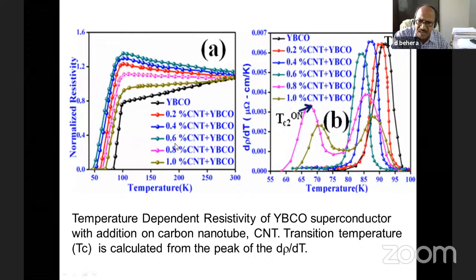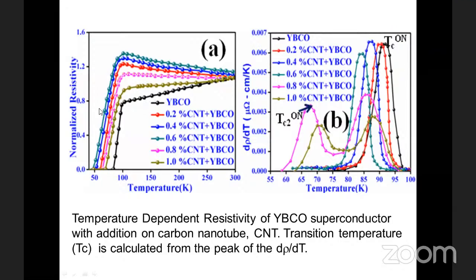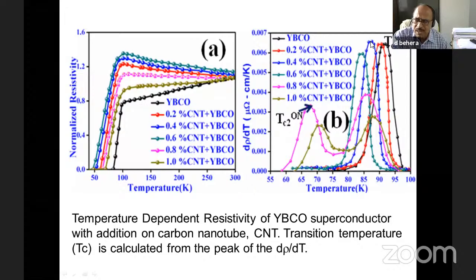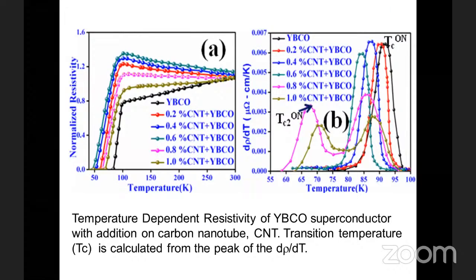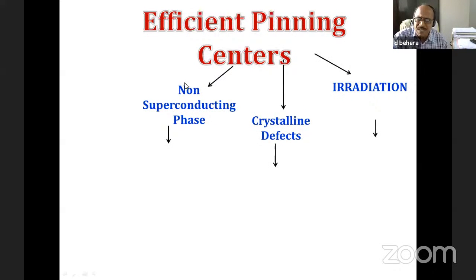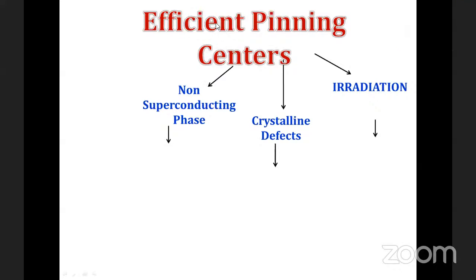My students prepare this material and measure the critical current density. The TC of the material can be measured from the derivative of the curve. It gives you a peak, and that peak shows the transition temperature of the material, which is more than 92 K. But our aim is not measuring TC, because this is a well-known thing. What they did is take YBCO, a superconducting material, and add some CNT, carbon nanotubes, in different concentrations. That means they want to create some defects. Okay. Now, if defects are there, what happens? In the process, they want to create some type of nano defects.